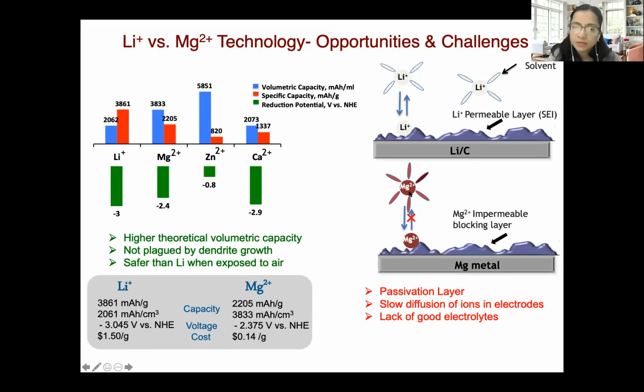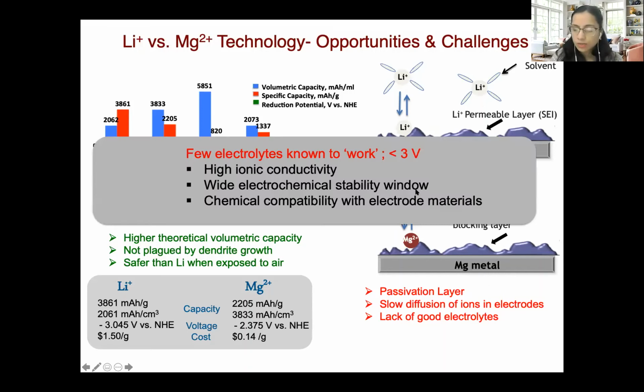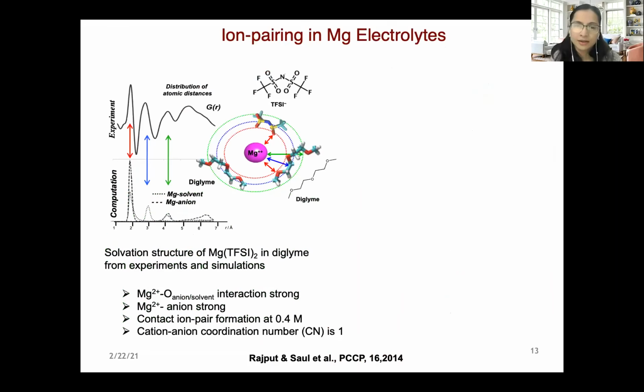Another problem with magnesium batteries is the slow diffusion of ions in the electrode because of their divalent nature. So if you want to commercialize magnesium ion batteries, we need electrolytes with high ionic conductivity, a wide electrochemical stability window, and chemical compatibility with both the electrode materials. So pretty much everything that you can expect from an electrolyte. In the search for these electrolytes, we begin our study with a very simple magnesium salt, magnesium with TFSI anion and diglyme solvent molecule. In this work, we combined experiments and simulations to zoom into the solvation structure around magnesium.